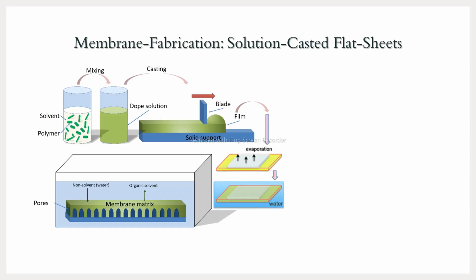The solution casting method consists of first mixing the polymer inside the solvent, then it is casted on a solid support. After that, either by evaporation or inside the water baths, the solvent is removed and pores are formed inside the polymer membrane matrix.